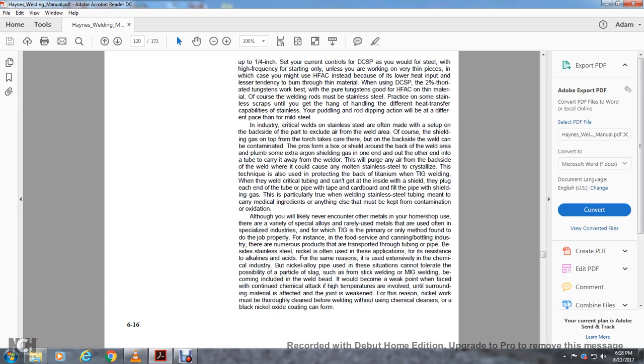The nickel alloy pipe used for this cannot tolerate the possibility of slag, such as from stick welding or MIG welding, becoming included in the welded bead. It would become the weakest point when faced with continued chemical attack, as high temperatures are involved until the material surrounding the joint is affected and weakened. For this reason, nickel work must be thoroughly cleaned before welding, without using chemical cleaners, or a black nickel oxide coating can form.